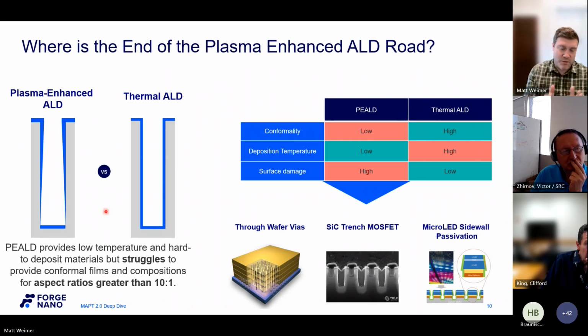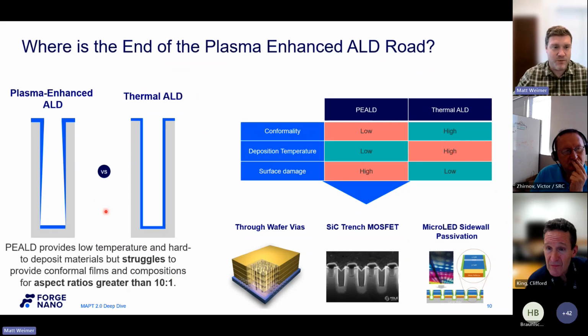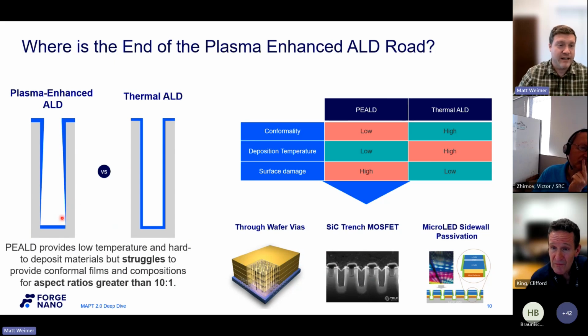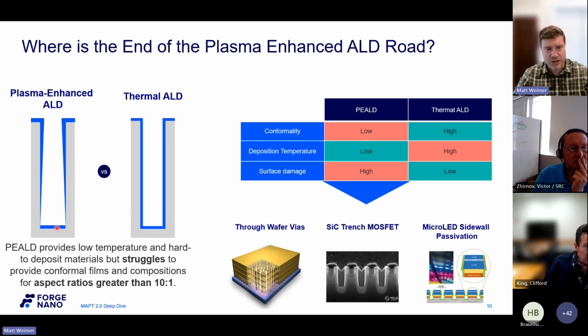So one of the cartoons that we like to draw here is with plasma-enhanced ALD, once you get to a certain aspect ratio, your film thickness will degrade. Now you might have thick film on the bottom, if you're using ions, if you have a directional aspect. If you're just using radicals, then this will go away as well. But of course, with thermal ALD, this is conformal. The one thing though that is sort of lost in this analogy is it doesn't capture the composition of this film as you're losing thickness.